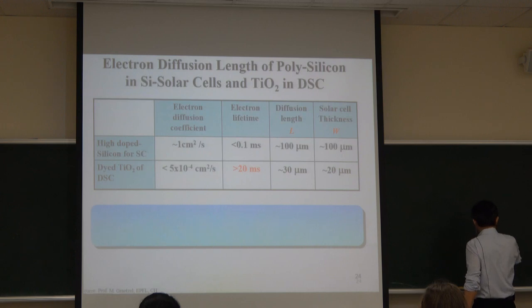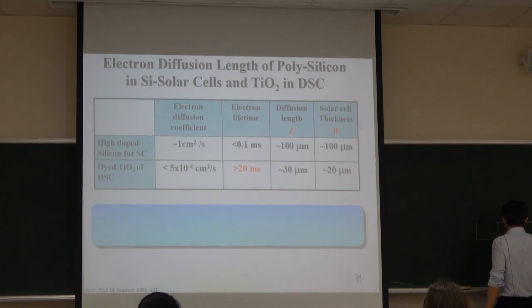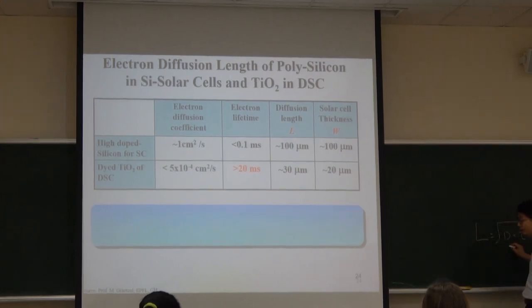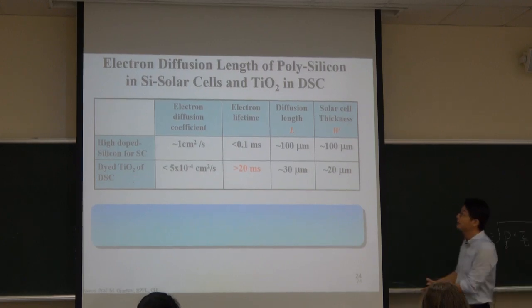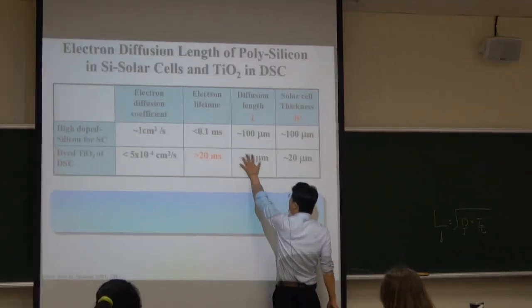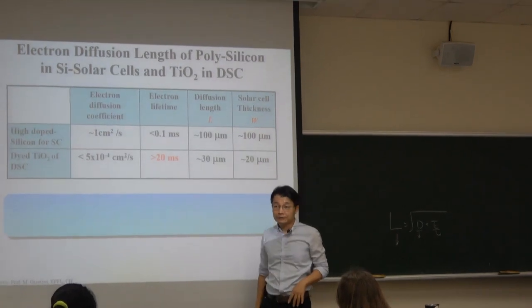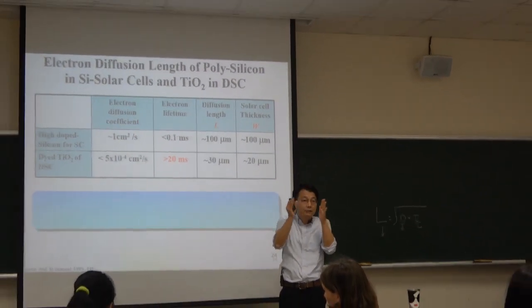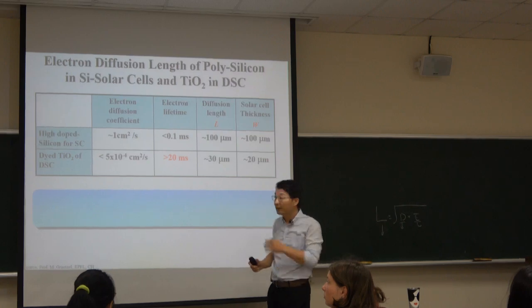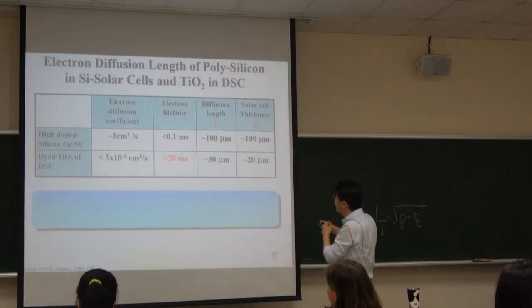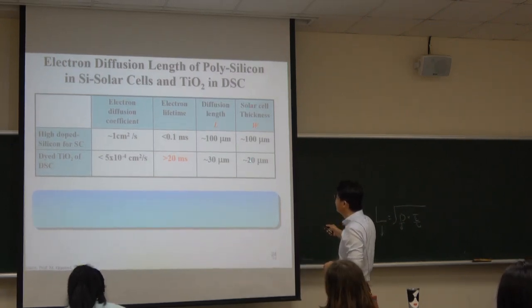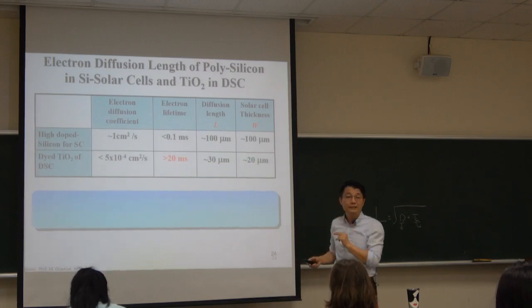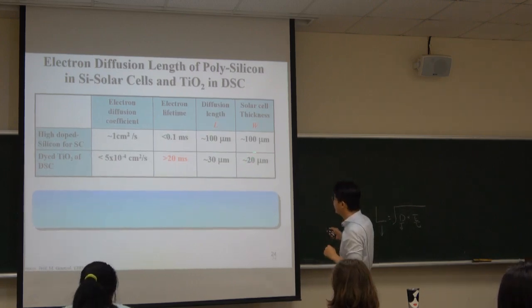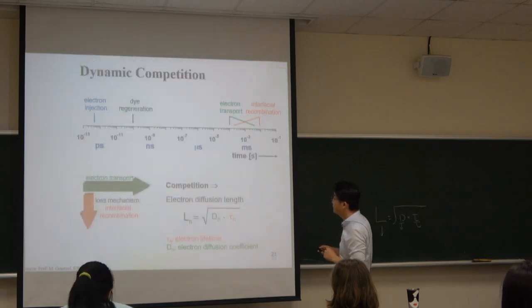Then you can calculate, because L equals the square root of D multiplied by tau, right? You have D, you have tau, so you can calculate the length. This total length could be approximately 30 micron, which means you can deposit 30 micrometer. That is the diffusion length. But usually you have to reduce it to 20 micrometer. Do you know why?